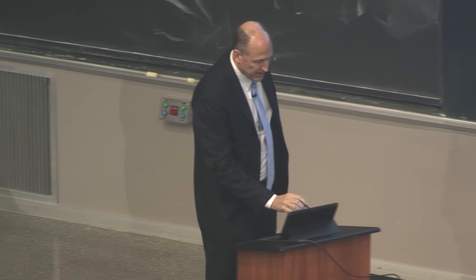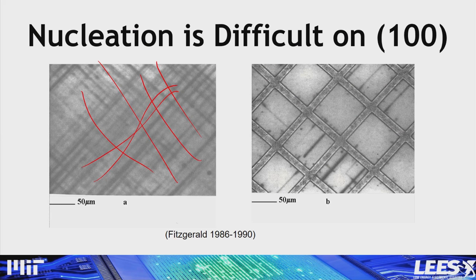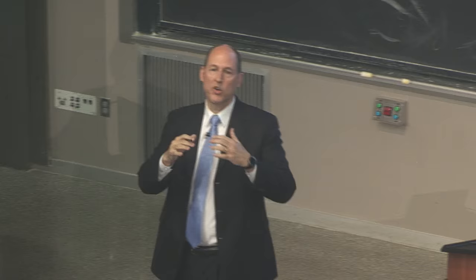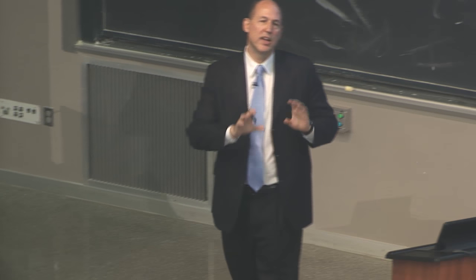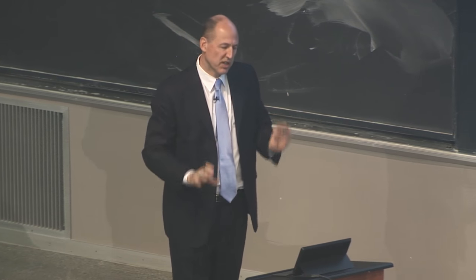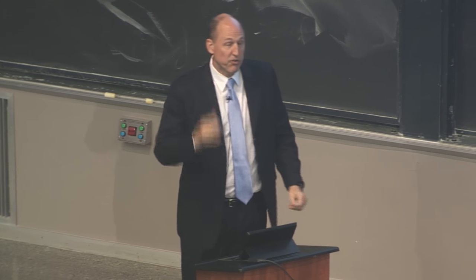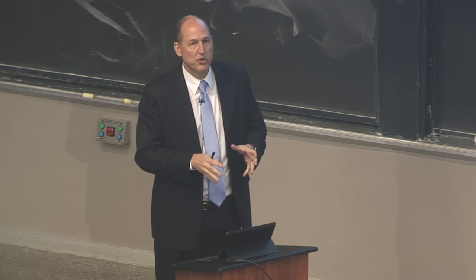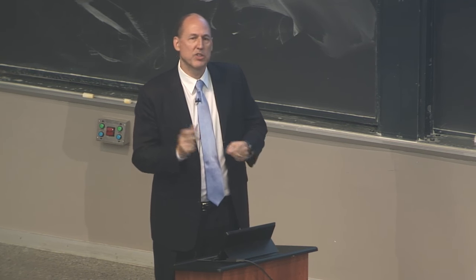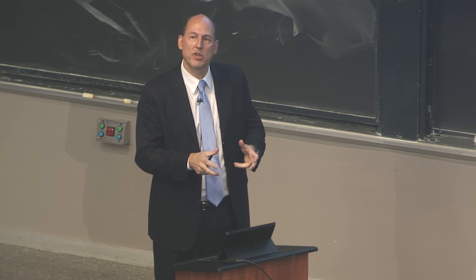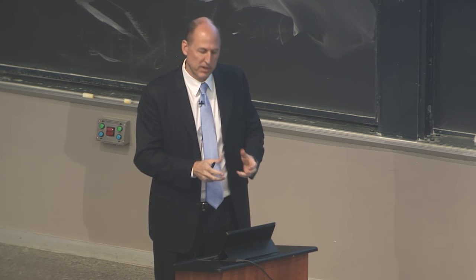What you see on the right is the same sample, where in some areas that have no nucleation source, you can build up strain far above the level that people thought would already bring in dislocations. So it starts to separate the thermodynamics from the kinetics in this problem, and it starts to give you ideas about how to manage and engineer. So the science leads to engineering of how you can control all this stuff, right?